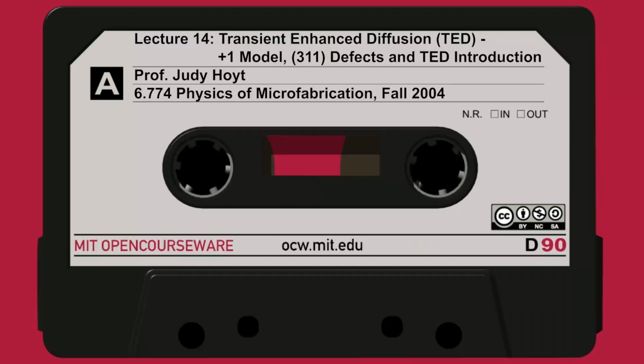And remember, when we were back here, doing this simple back of the envelope derivation on page 18, we said we ignored the diffusion flux that went into the bulk and recombined. For a simple back of the envelope calculation, we said all the interstitials diffuse towards the surface and recombine there. When you get them deep enough in the bulk, that's not necessarily the right model. Again, it's just to show this is a little back of the envelope. So in a real case, the amount of TED will actually saturate at some energy. So take this Rp dependence with a grain of salt.